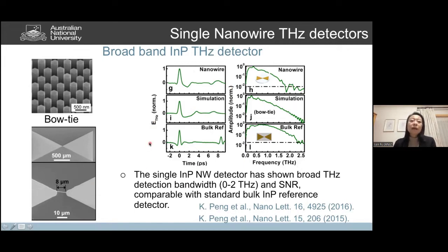So we want to see, when we use nanostructures such as nanowires, can we also use them for terahertz detection? Because they're tiny, they can be used for really nice near field spectroscopy applications. And also because using nanowires, we can have a very small device volume, thereby we can significantly reduce the dark current of the device and achieve a good signal to noise ratio. So that's really the motivation behind that.